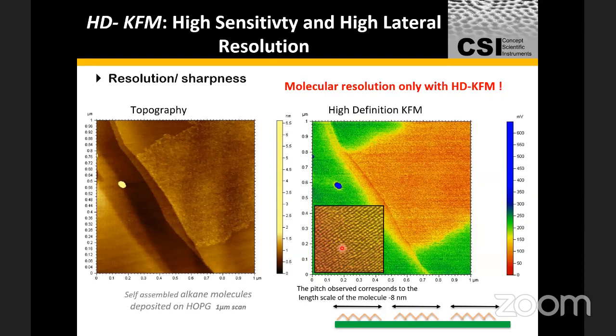Kunal, I have a request. Whenever you show these nice results, can you also mention to the students the conditions, like whether these are UHV measurement or ambient conditions, and what was the state? Those are very important, actually. So was it taken in ambient or in a UHV chamber? I cannot say for 100% because I didn't make the measurement, to be honest. I believe these are ambient measurements, but it's quite possible that these experiments were conducted when the sample tip environment was purged with argon or a similar inert gas.